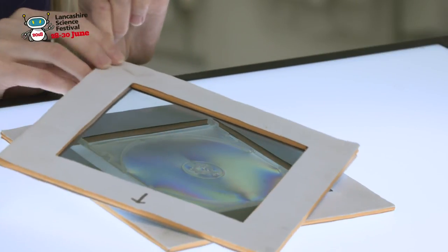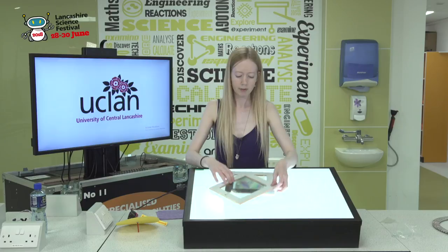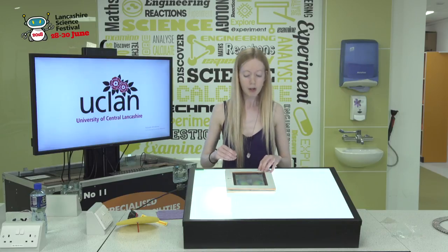So this is a similar sort of thing, but now what we're seeing is actually the stress lines in the material. So when this plastic was made, some parts of the plastic are going to be a little bit more stressed than other parts, and all these stress lines show up in between the polarizers.